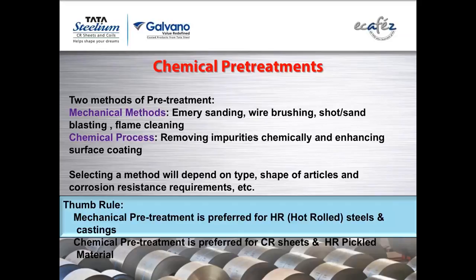Now there is a thumb rule that mechanical pretreatment is normally preferred for HR, that is hot rolled steels and castings, and chemical pretreatments are normally preferred for CR sheets and HR pickled material. Now on HR, you will find a lot of mill scale, and this mill scale can only be removed by mechanical pretreatment like blasting, or you can pickle it with very highly concentrated acids, which is again not a highly recommended process, because if you are doing some deep draws on pickled material, they might crack because of something called hydrogen embrittlement, which happens while pickling. So usually first preference goes to blasting.